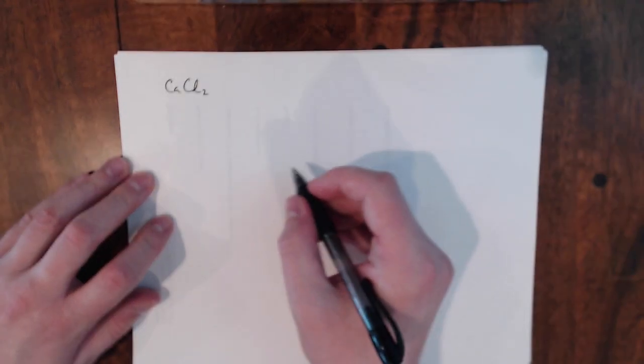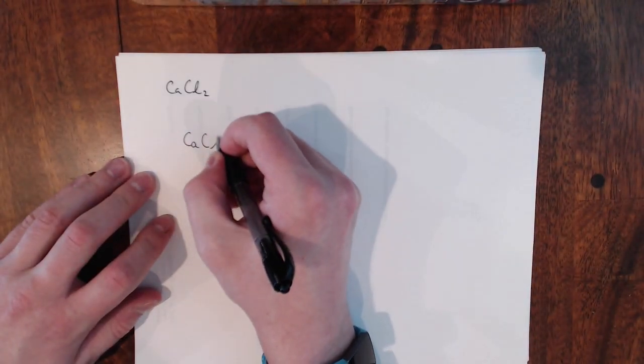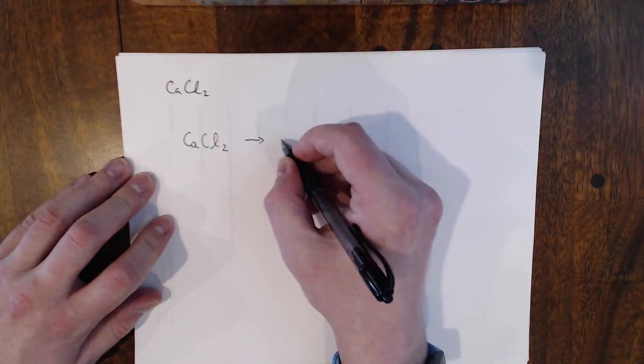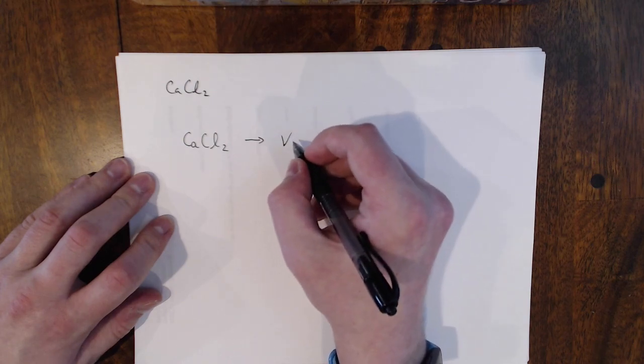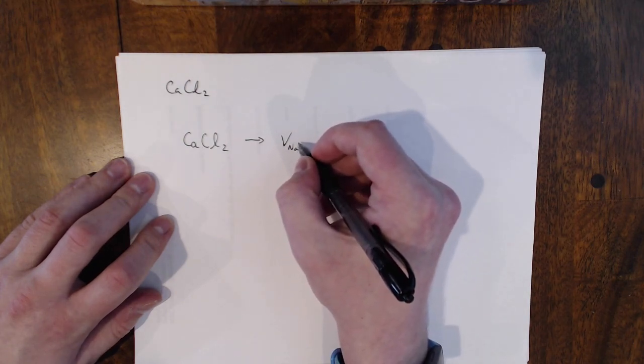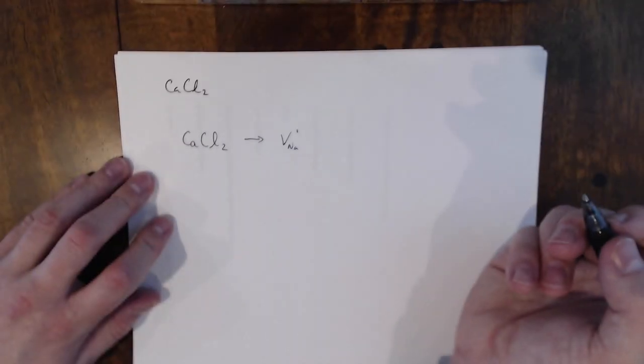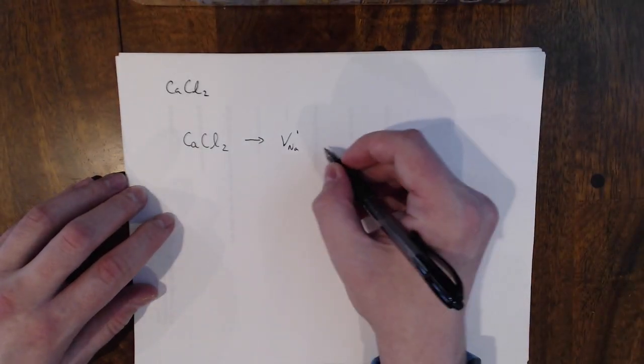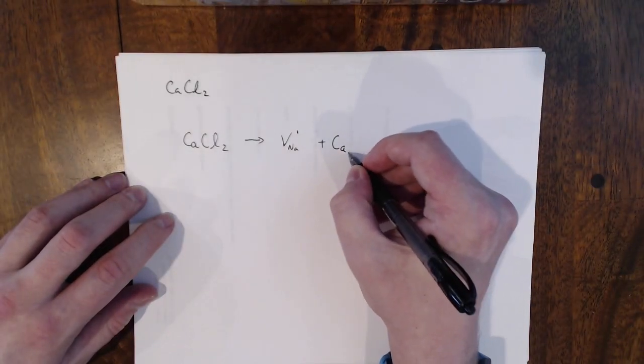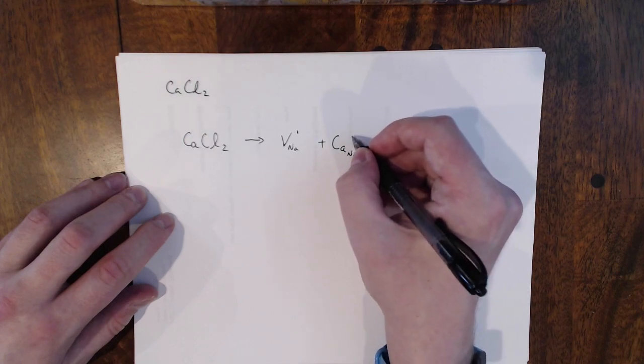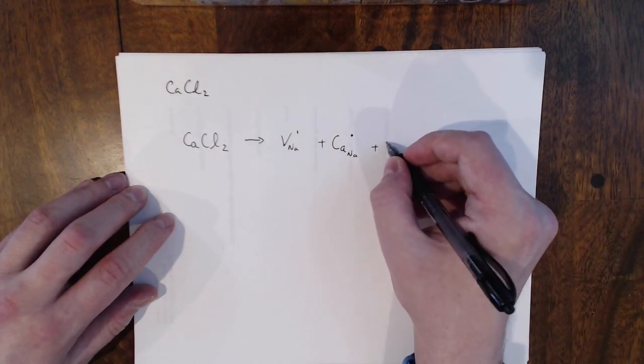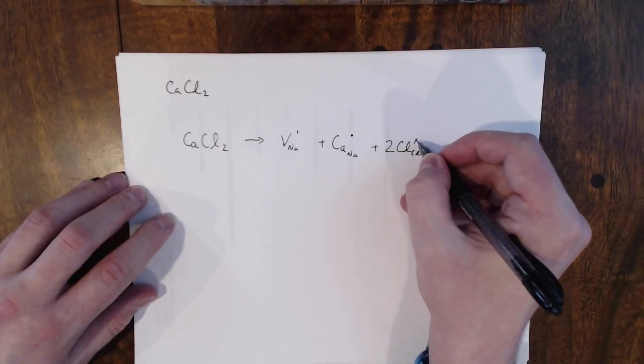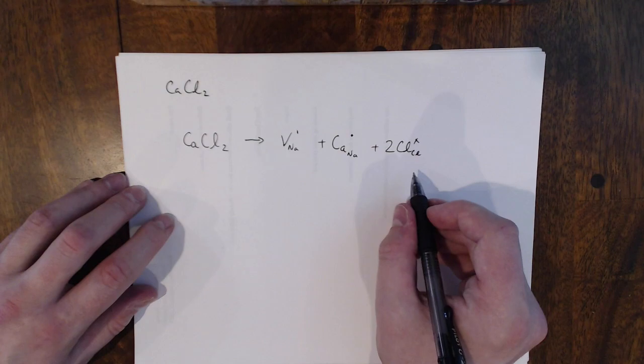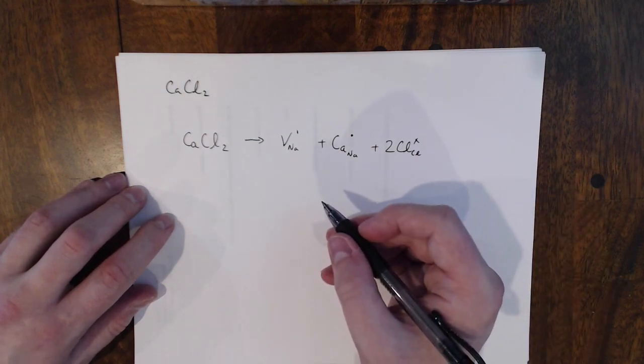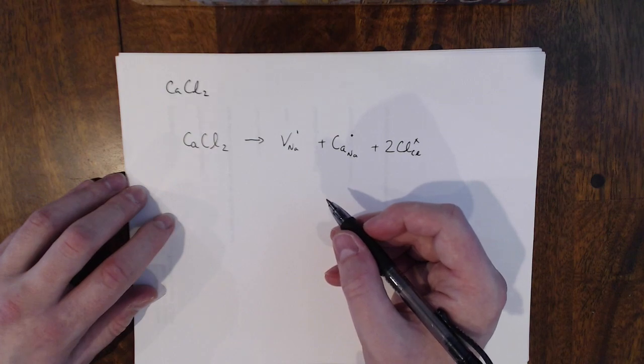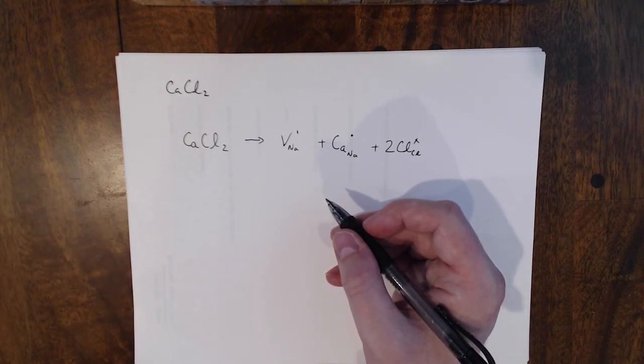That's our dopant. So from the previous section of this class, we wrote these defect reactions. When we add in that calcium chloride, one of the possible reactions that we can get is vacancies of sodium when we add in the calcium for sodium, because it's going to have a positive charge, and then we have to also add in these chlorine. So if this defect reaction doesn't make sense, or you're wondering where we got it, go back to that previous section on defect reactions.